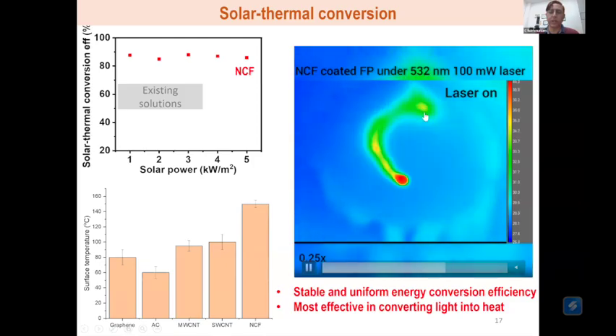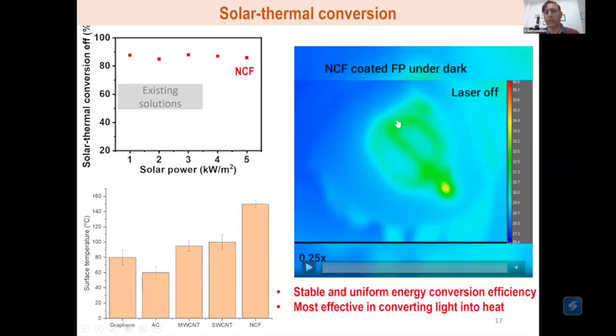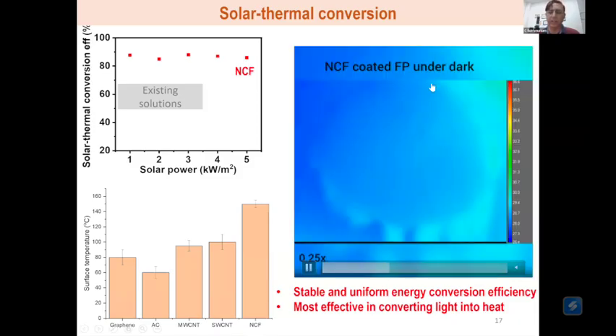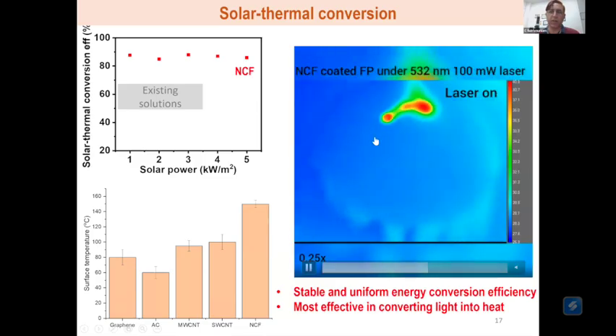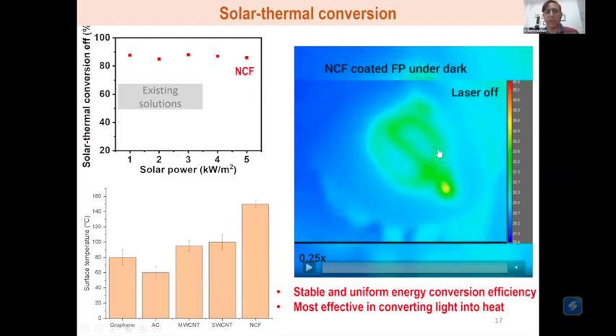So you bring in a laser pointer, which is normally what you use for a PowerPoint presentation, or any presentation, and you try to draw a symbol on the surface, and you can see that it creates a beautiful heat map signature. So as the laser pointer comes in, I'm just running it again, you see a hotspot that is being created, which is resulting in a temperature difference of already 5 to 7 degrees, created by just a laser pointer, which is about 100 milliwatts in power. So this is, again, going back to the exceptionally high conversion efficiency the material has.